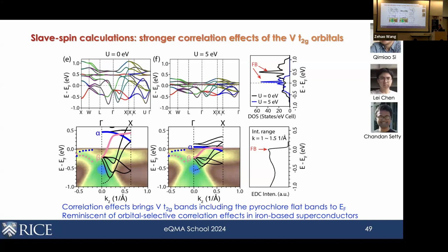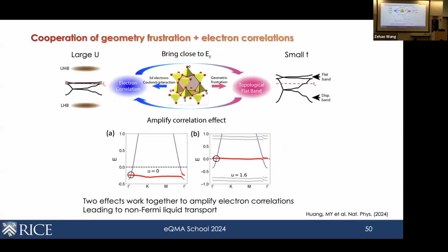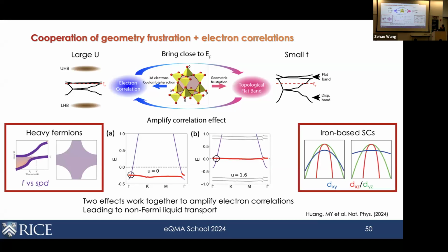So here, one step above what we found from cerium-2, is that there seems to be two effects at play. One is the destructive interference, which gives us the topological flat bands in the first place, and that's by quenching the kinetic energy. And then at the same time, there's also electronic interactions, which further normalize the states towards the Fermi level. And it's these two effects that are both in play that really amplify the correlation effect in this material, therefore producing this flat band that we see at the Fermi level. Right? So in that way, it's actually reminiscent of the situation in heavy fermions and also the iron-based superconductors with the strong correlations.